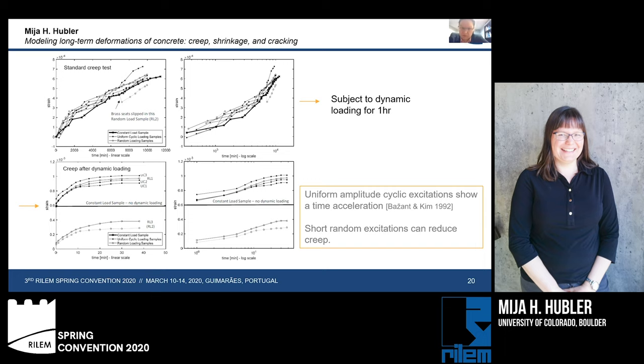So the interesting observations we can make here is that uniform amplitude cyclic excitations show a time acceleration of the long-term behavior. This agrees with previous publication by Bažant and Kim in 1992. But what has not been previously observed is the fact that short random excitations can reduce the creep in long-term deformations of the sample.